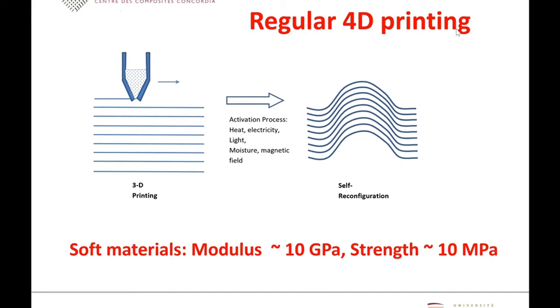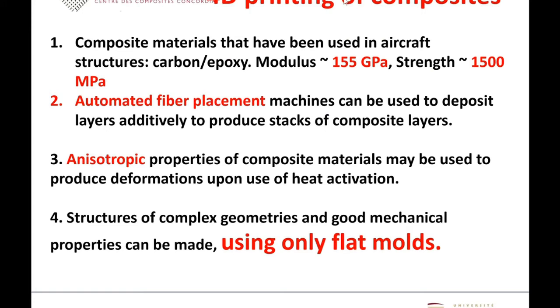And what I feel is that we need to distinguish that for the case of 4D printing of composite. In this case, rather than using soft material, I think the last speaker talked about the biomaterial, something like the cellulose fibers, and they have some kind of properties. But compared to things that I studied, carbon epoxy, these are materials that have very high mechanical properties. The modulus is about 155 GPa, the strength is about 1,500 MPa. And like I said, these are materials that have been used in making components of aircraft, automobile, or wind turbines. So they are very stiff and strong. So that is one particular difference between the 4D printing of composite and the regular 4D printing.